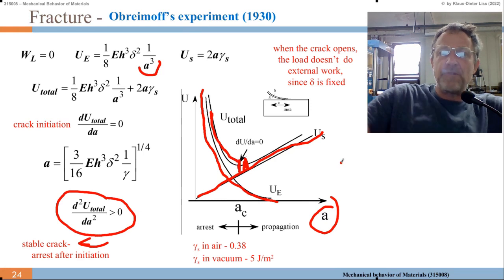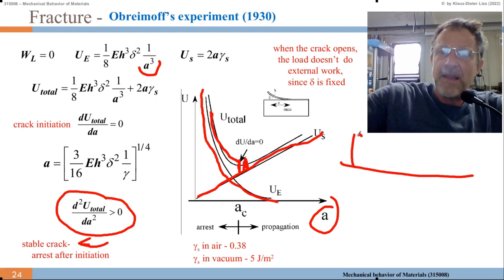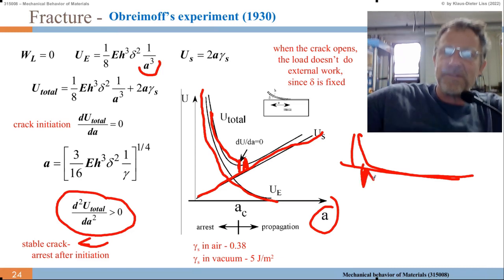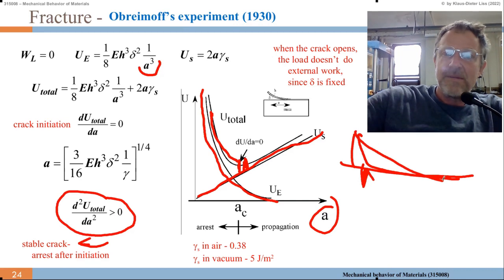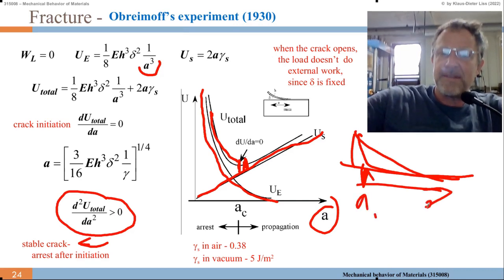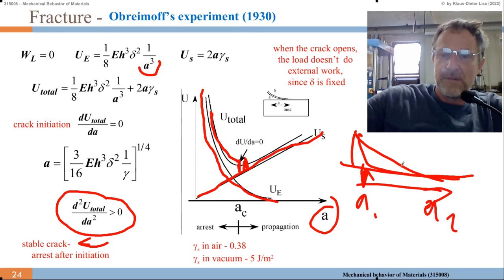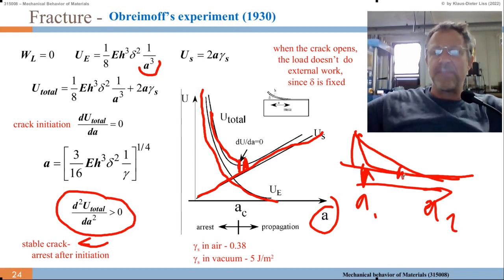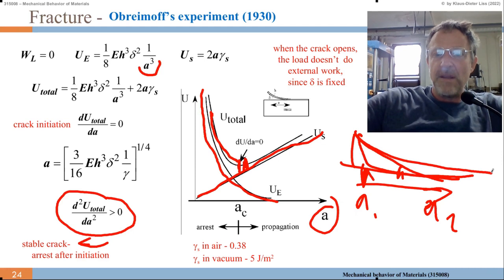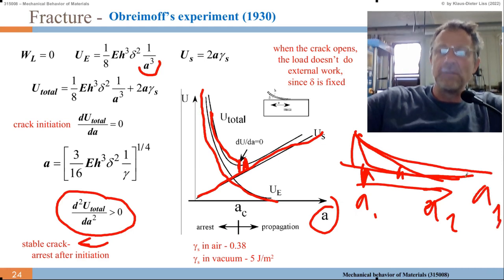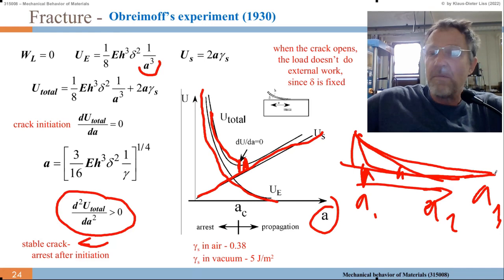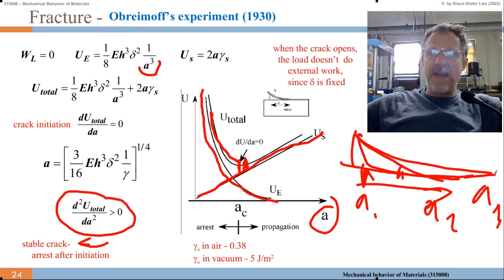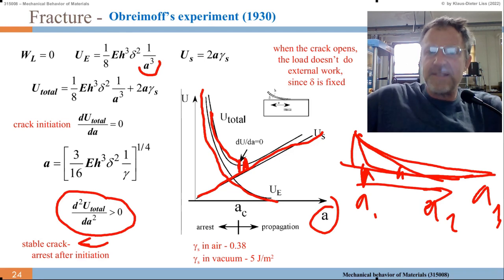And of course, you can imagine this, right? It makes total sense. If I lift up a piece and it has a steep angle, then I have a large stress concentration there. Now as A grows - this is A1, this is A2 - the angle becomes shallower, and I get less stress concentration at the crack tip. And eventually, if A3 becomes too long, then I create more surface energy than I would gain with the release of strain energy, so it would not propagate.